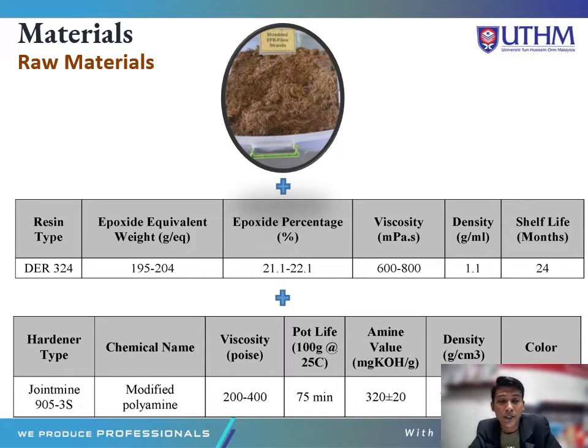This is my raw material. The above one is the PEFB, which will be ground. For the resin type, I will be using the DER 324. The epoxide equivalent weight is 195 to 204, and the epoxide percentage will be 21.1 to 22.1%. The viscosity is around 600 to 800. The density is 1.1. The shelf life is 24 months.